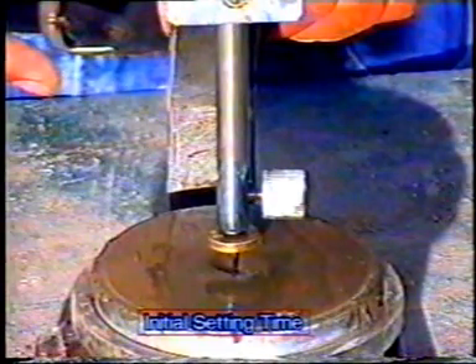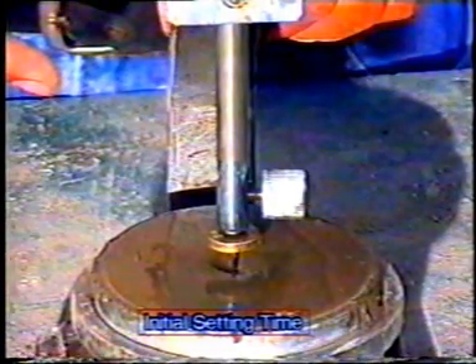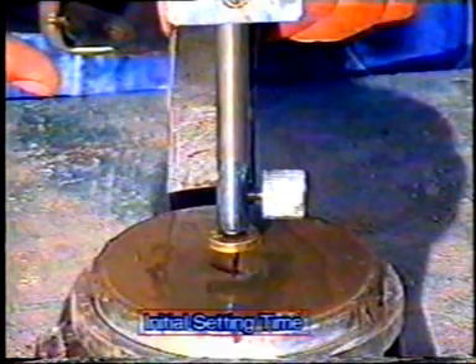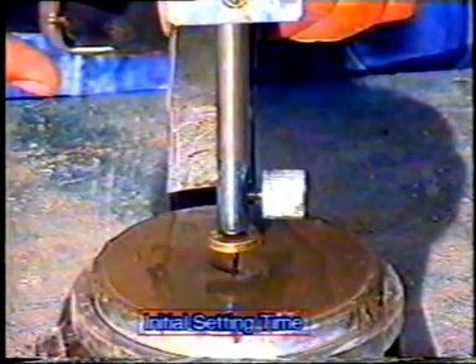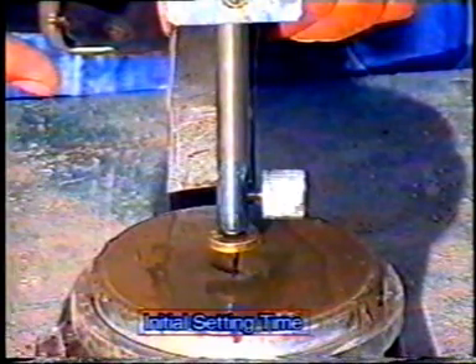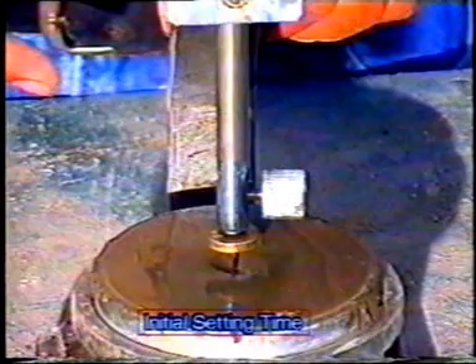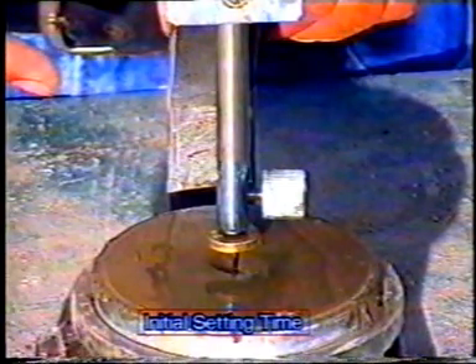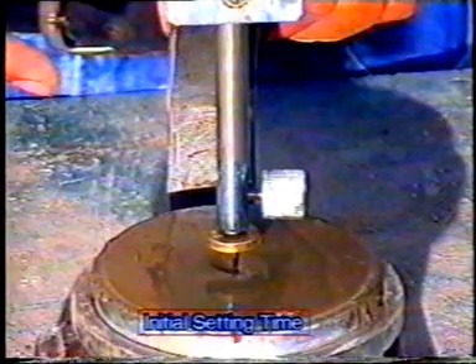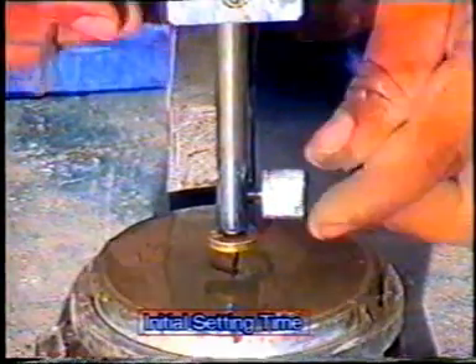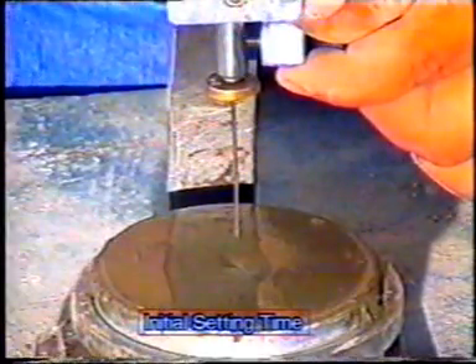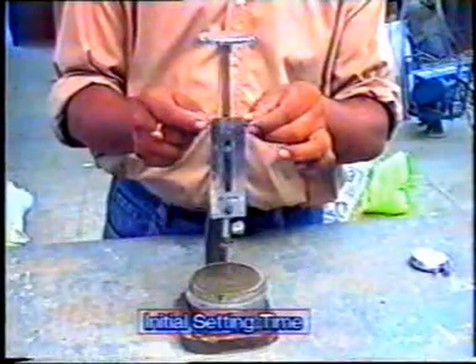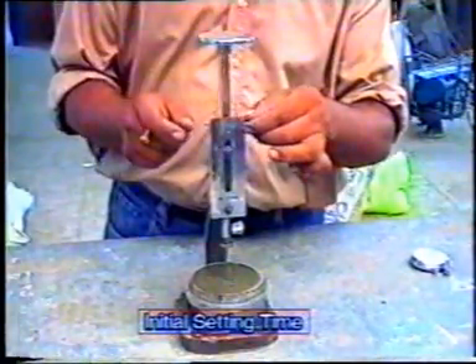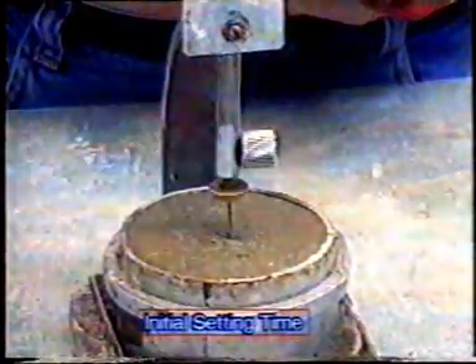As you can see, the needle has completely pierced the test block. That means that the initial setting time of cement has not yet come. Repeat the process of releasing the needle at regular intervals until the needle fails to pierce the block for 5 plus or minus 0.5 mm measured from the bottom of the mold.